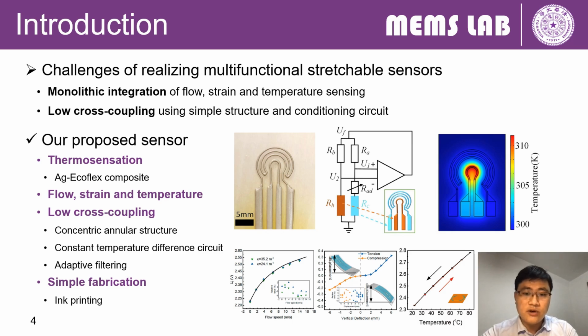Here, we propose a multifunctional stretchable sensor based on thermosensation, enabling multi-sensations of flow, strain, and temperature. We develop a simple and low-cost ink printing technique using homemade silver Ag-Ecoflex composite ink to fabricate thermosensitive ribbons on Ecoflex substrate to form the stretchable sensor.